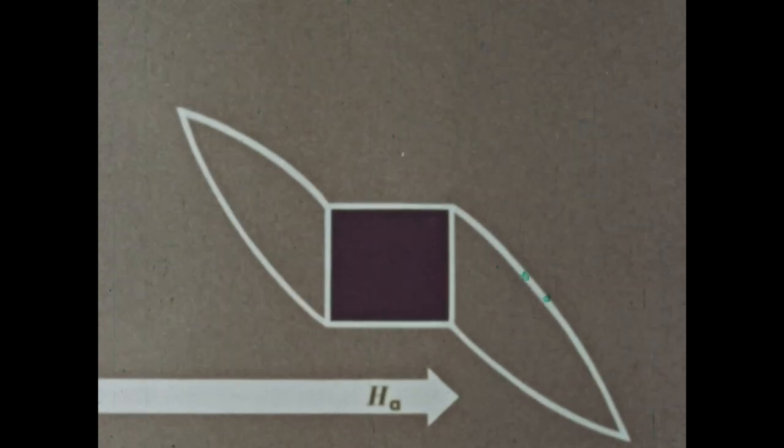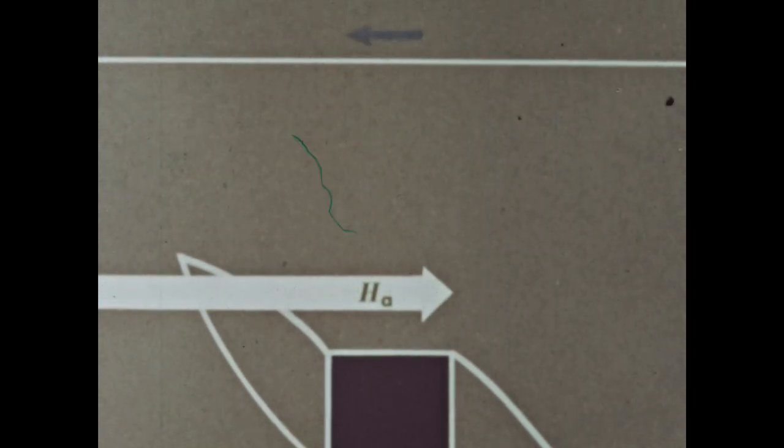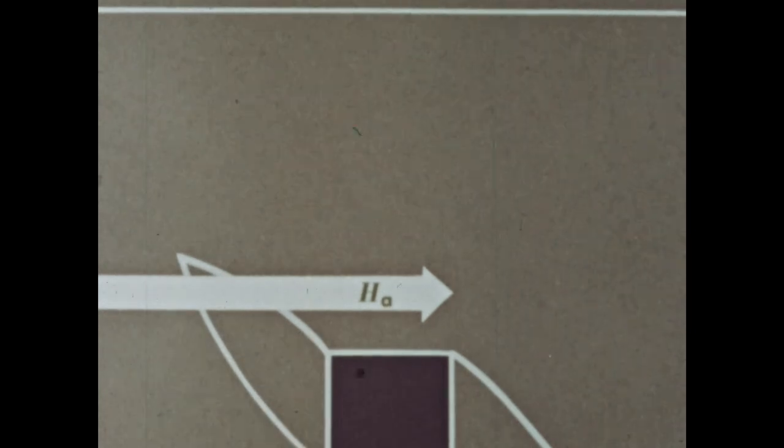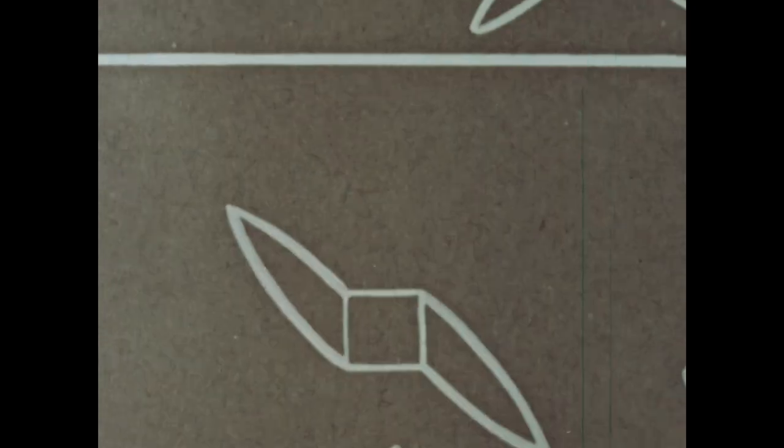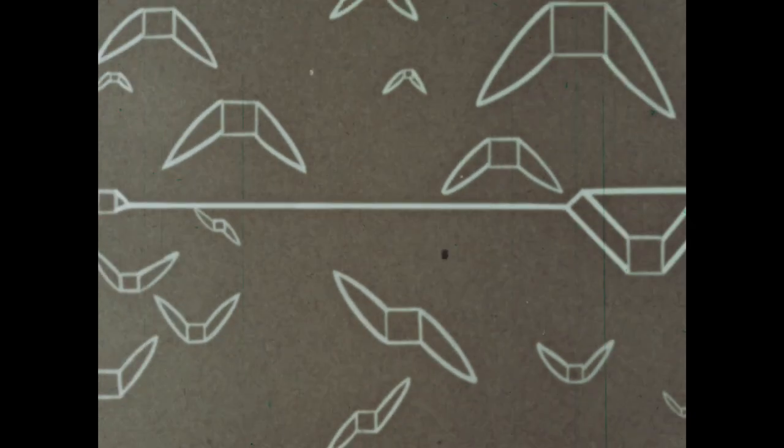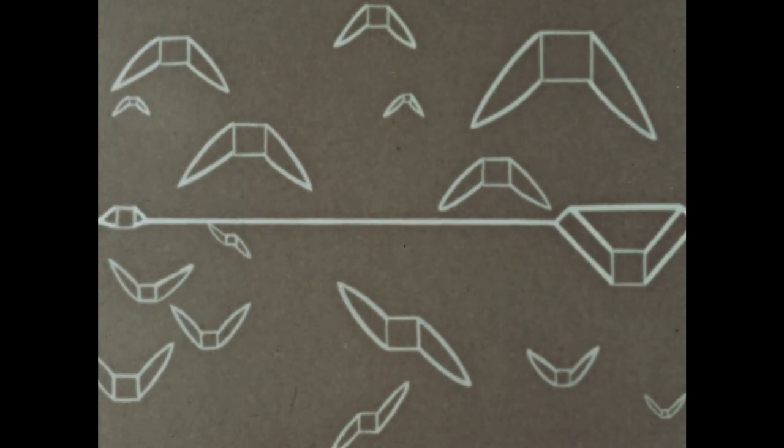Now, the secondary structure no longer pulls back on the primary domain wall, so that if we withdraw the field, the wall tends to return only slightly. This happens because in any real situation, there will be many secondary structures attached to the primary wall at any one time.